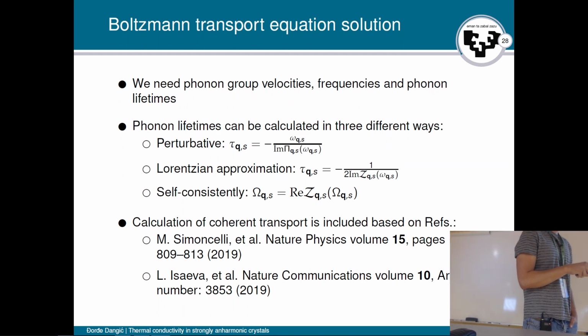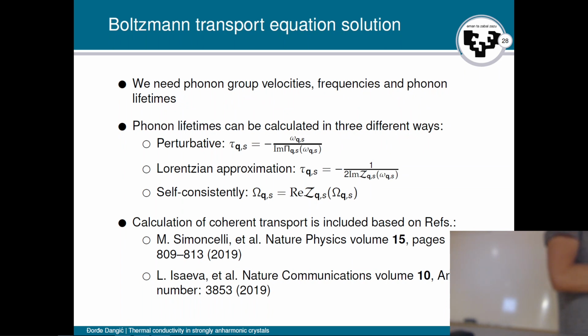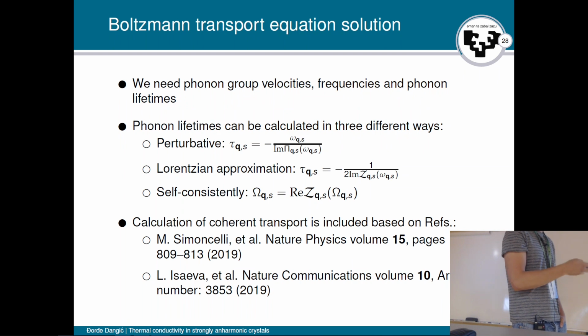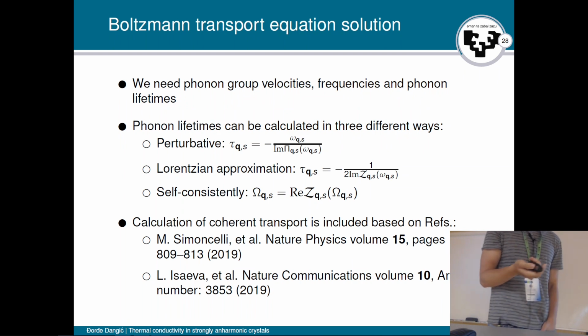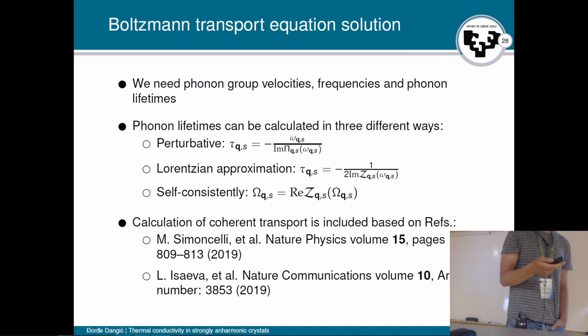Also, there is a Lorentzian approximation. The Lorentzian approximation is the one that we get from the low anharmonicity limit, and this is the one that is actually implemented in SSCHA as a default. These two are practically the same in the low anharmonicity limit, but you can see some minute differences if the anharmonicity is large.